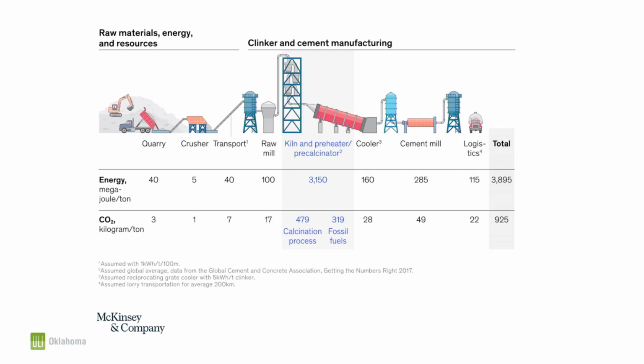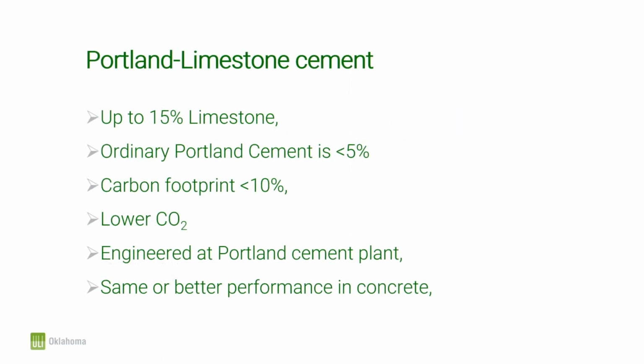Now, that calcination process is inevitable. We cannot do anything about it. That's the way the chemistry works in order to produce that calcium oxide and release all that CO2. So how do we limit the use of that Portland cement? If you remember when I talked about the clinker being the main product to produce Portland cement, what we're doing nowadays is mixing a lot more of that raw limestone flour with that clinker. Normally, the American Society for Testing and Materials, ASTM, will allow Portland cement to operate for a Type 1-2 at about 5% of raw limestone, okay? What Portland limestone cement is doing is pushing that 5% all the way up to 15. Currently, cement plants are actually adding about 10% more.